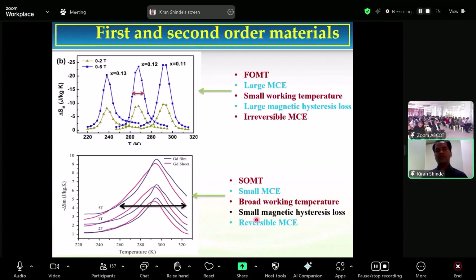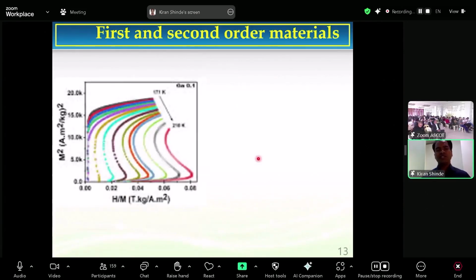So when we use this material for application purpose, these are not feasible. But when we use the second order phase transition material, we can get the reversible magnetic entropy change curve. So when we study this kind of material, first we have to check whether these are first order or second order phase transition materials, and how we can determine that. Using this Arrott plot, which is nothing but the square of magnetization plotted against the magnetic field divided by magnetic moment, we can get this kind of graph, which is called Arrott plots. And for first order phase transition material, we can see that the slopes of these Arrott plots at different temperatures include positive slopes and negative slopes.